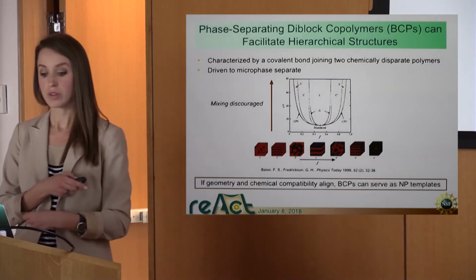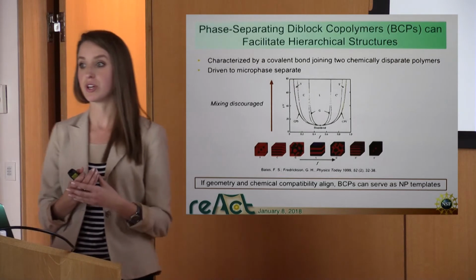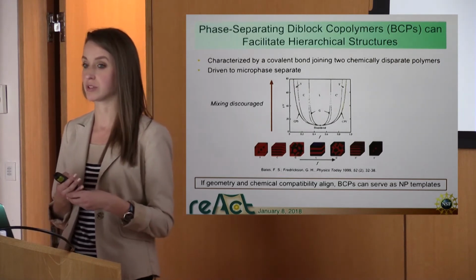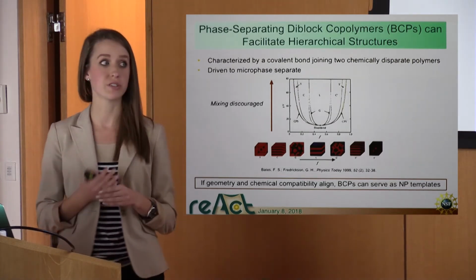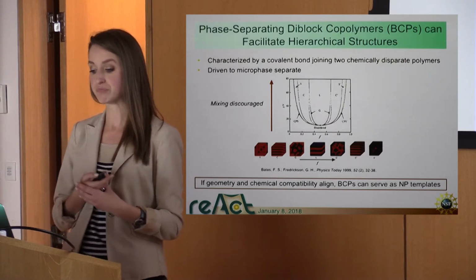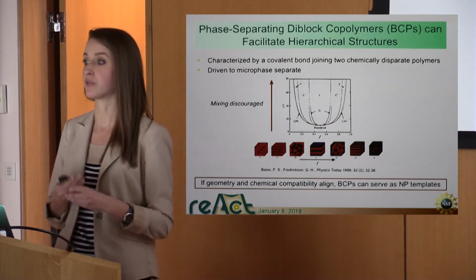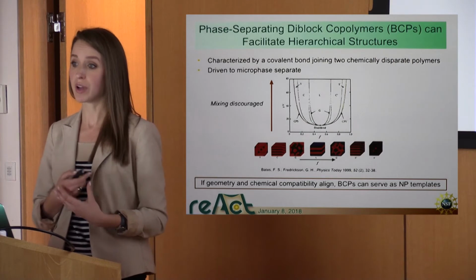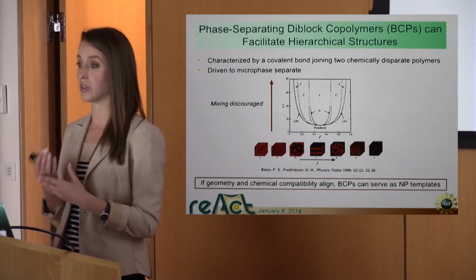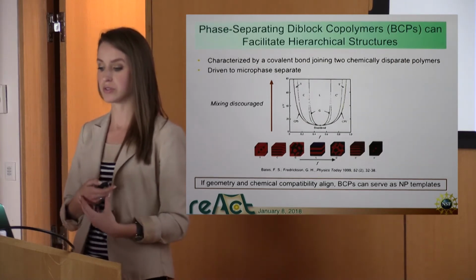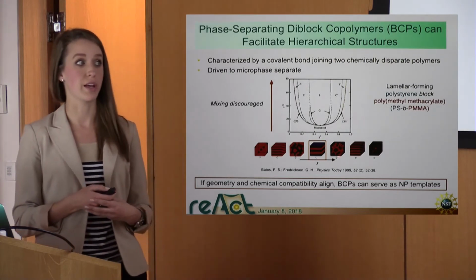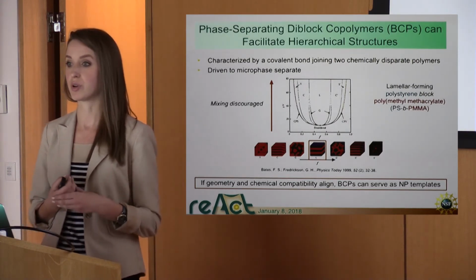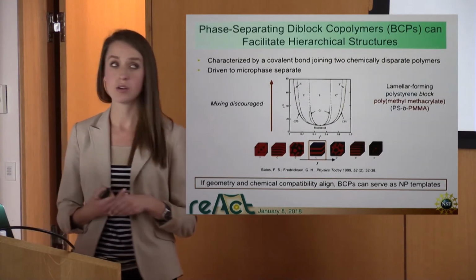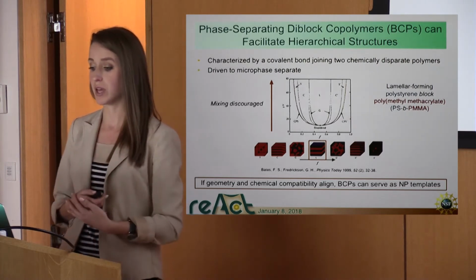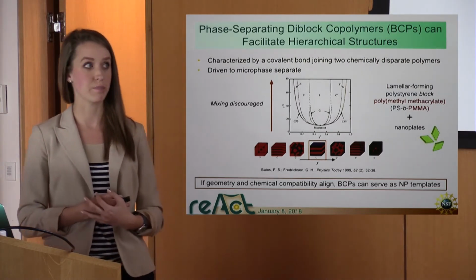So if the geometry of the template of these block copolymers and the chemistry matches the particles we want to incorporate into them, they can serve as templates for nanoparticles. So my work in terms of aligning non-spherical nanoparticles, I am working with a lamellar forming block copolymer, polystyrene-block-PMMA, or I'll refer to it as PS-b-PMMA, and a nanoplate system.